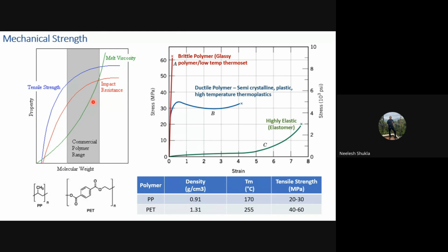So the downside is that if you want very high performing, very high strength polymers, you can keep on adding more and more polymer chains, but your viscosity would increase, and that would have a counter effect in terms of processing. You would have to reach higher and higher temperatures. And then there are some polymers which, although they are not thermosetting, have a large molecular weight that makes it very difficult for them to be melted and processed. One such polymer is ultra high molecular weight polyethylene. You can say it's the brother or sister of polyethylene, which is the simplest polymer, but the number of polymer chains is many more as compared to normal polyethylene, HDPE, LDPE. That's where the secondary forces come into the picture, and they give it very good strength, better than polyethylene, but they also increase its viscosity very high, so you just can't easily process it into an article the way you could with HDPE or LDPE.